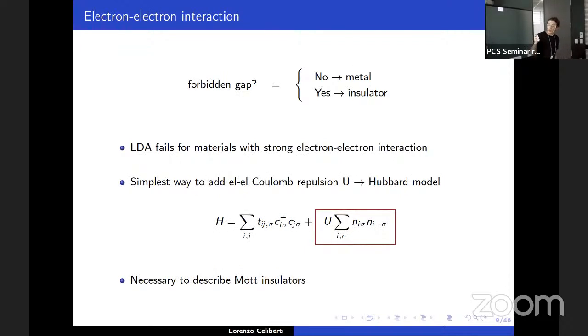Okay. So these materials where the LDA fails are usually materials with strong electron-electron correlation, which can be represented in a model Hamiltonian by the Hubbard model, which is not solved yet, as far as I know, but many people are working on this. This kind of interaction term, which represents the Coulomb repulsion between electrons on one site, is necessary to describe Mott insulators. These are materials that are predicted to be metals from the standard band theory, but are actually insulators because of this Coulomb on-site repulsion.